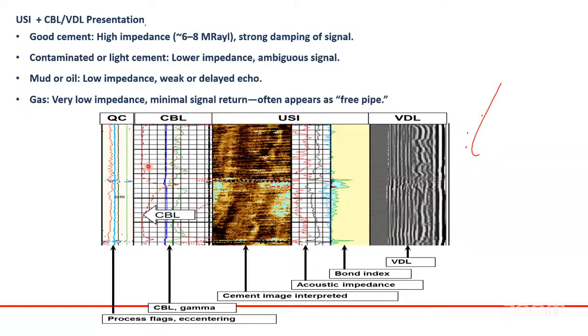This is a USI, CBL, VDL representation, as you see. A good cement has high impedance, 6 to 8 Mrayl, with strong damping of the signal. Contaminated or light cement has lower impedance and an ambiguous signal. Mud or oil has low impedance and a weak or delayed echo. Gas has very low impedance and minimal signal return, and appears as free pipe.